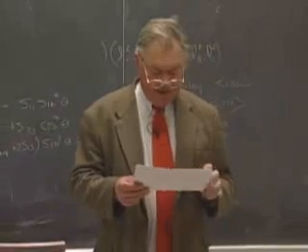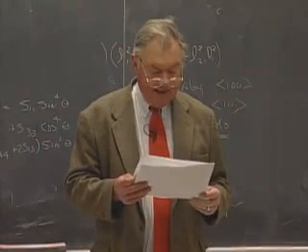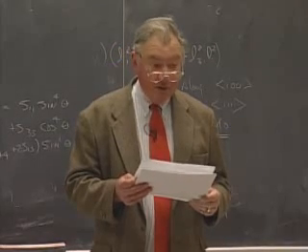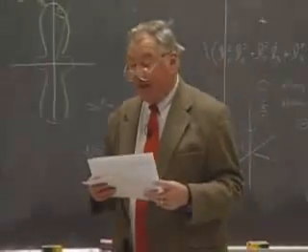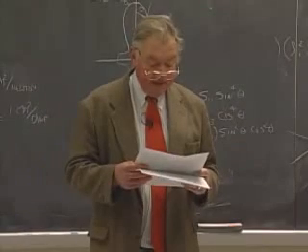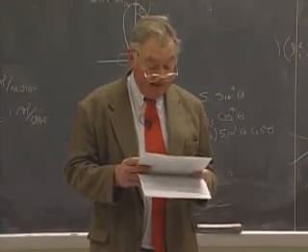This is interesting because you'll remember there was an additional equality between the stiffnesses called the Cauchy equality, which was supposed to hold for physical reasons, not for reasons of symmetry, if the forces were central, if the crystal was under a state of no stress, and if all of the atoms were situated at a center of symmetry.